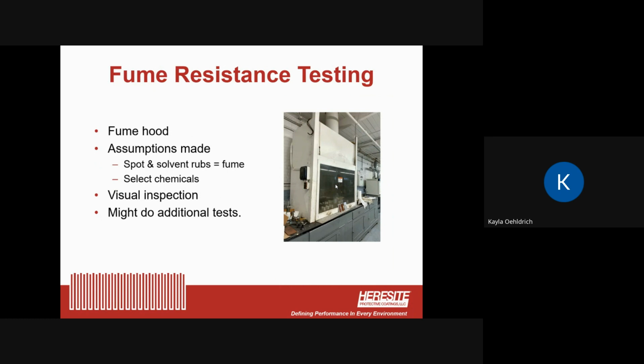It's important to note that there are some assumptions made when we do fume resistance testing. If it passes a spot test and a solvent rub test, there's a really good chance that it's going to pass a fume resistance test. There are some select chemicals where that may not be the case, but we know what those are before they get here, and before we do testing on it. So we don't do nearly as much fume resistance testing as we did years ago.